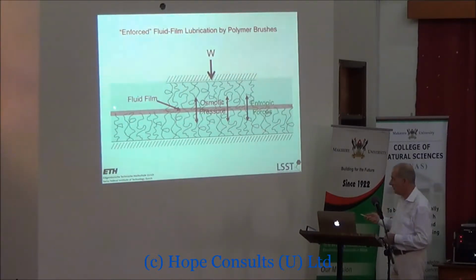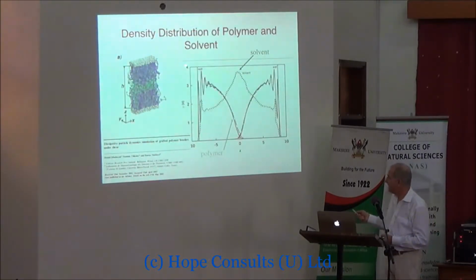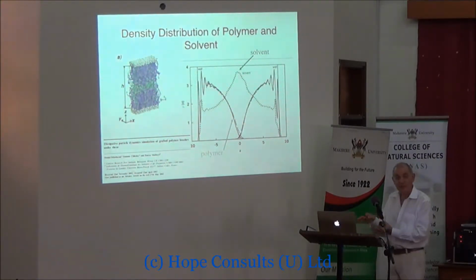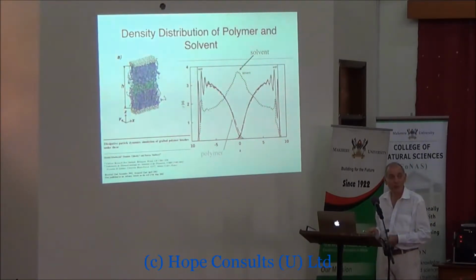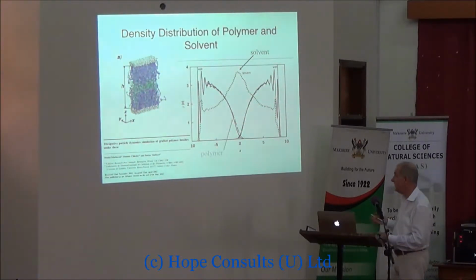Now at the interface, although it's not obvious from this drawing, the way I've drawn it, there's a fluid film. And that fluid film is there because the concentration of monomer as you move out from the surface is not constant, the way I've drawn it here, but it actually falls off in a parabola. So in the central region where the two brushes meet, there's actually much less monomer than at the walls. And so in the middle, just because of the brush physics, we have a low concentration of polymer, a higher concentration of solvent. And so that's the fluid film where the sliding happens when we have one brush sliding over another. So we're giving it a fluid film, even in the absence of any hydrodynamic forces, which is what we normally associate with fluid film lubrication. But in this case, even when it's stationary, there's a fluid film there.